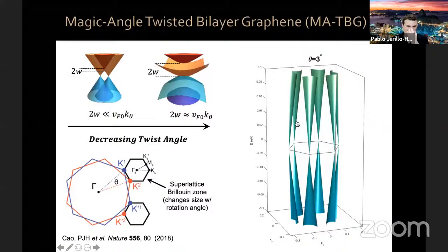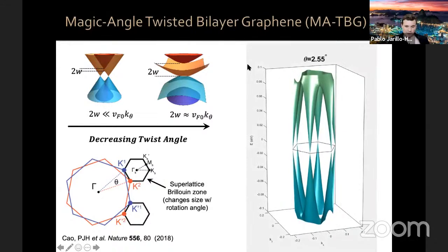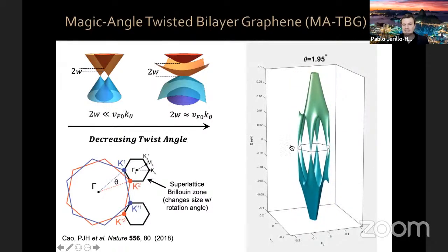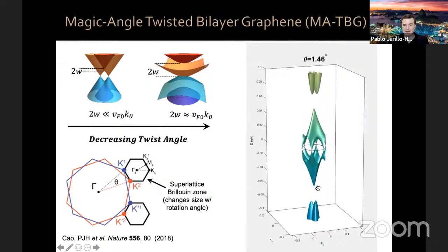So this is an actual calculation of the electronic structure. This is energy versus Kx and Ky. I'm going to click run on this video. This angle will go from 3 degrees towards the magic angle. This is for twisted bilayer graphene at 3 degrees. This looks just like regular graphene within this energy window. As I click go, you see that the electronic structure gets massively reconstructed. There are these band gaps. And now at 1.1 degrees, this band is going to become very flat. You see, very flat there.